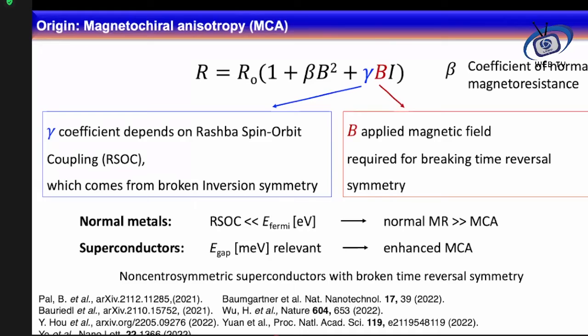Okay, in normal metals, we know that the relevant energy scale is the Fermi energy, and the Fermi energy is very high compared to spin orbit coupling. So this chiral magnetoresistance effect will not be that strong there, because spin orbit coupling is not really efficient. But in the case of superconductors, the energy term is the superconducting gap energy, and that energy is on the order of milli-electron volts instead of volts like the Fermi energy. So in a superconductor, spin orbit coupling has to compete with this gap energy, which is not very high. It means that the effect of spin orbit coupling must be very strong in superconductors, and in this way we can very easily get this non-reciprocal transport.